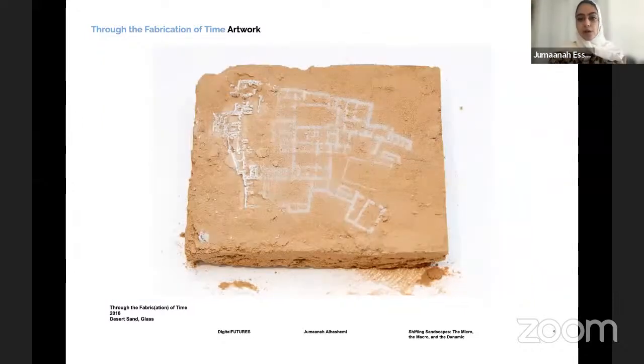And so this is also another trial into trying to see, well, if I were to use another kind of sand, which is not really silica sand, that doesn't really have as much silica properties, like desert sand, for example, and really trying to use it with certain water-based binders, such as sodium silicate, that has some silica components in it, and forcefully allowing that glass to emerge on the surface. Which is also another body of work that has been showcased across the United Arab Emirates.